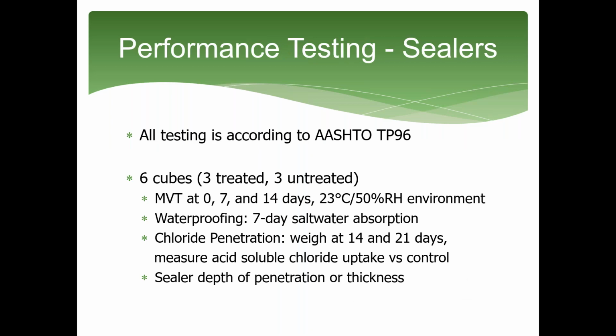For concrete sealers, testing is performed according to AASHTO TP96. 3 treated and 3 untreated cubes are stored at conditions of 23 degrees C and 50% relative humidity, and they're tested for moisture vapor transmission at 0, 7, and 14 days. The waterproofing ability is tested by measuring the weight gain following 7 days immersion in a 15% sodium chloride solution. The chloride penetration is tested by continuing the saltwater immersion and weighing the cubes at 14 and 21 days.